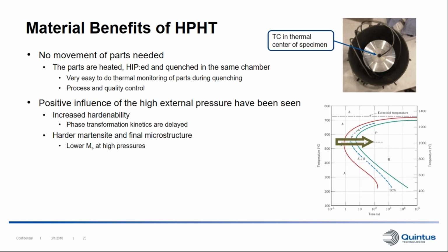Another interesting benefit, which mostly connects to the process and quality control when doing heat treatment, is the fact that we're not moving the parts anywhere when we're processing them in high-pressure heat treatment. The heating, the hipping, the quenching is all performed in the same chamber. If we look at conventional furnaces, you normally have a furnace chamber and a quenching chamber, or you have the furnace and the salt bath. So you have to move the components between different chambers or bath. But since the component stays in the same position during the whole cycle, it's very easy to monitor the temperatures around the component and also inside the component even.